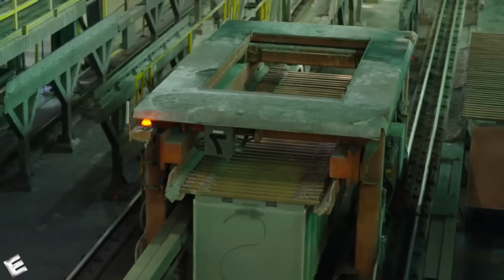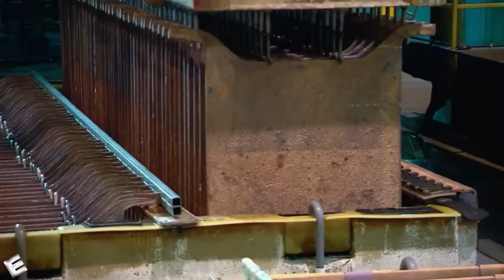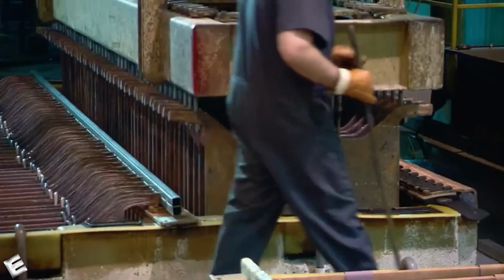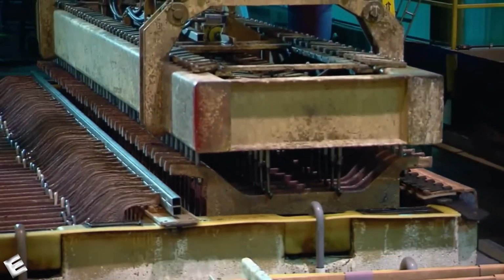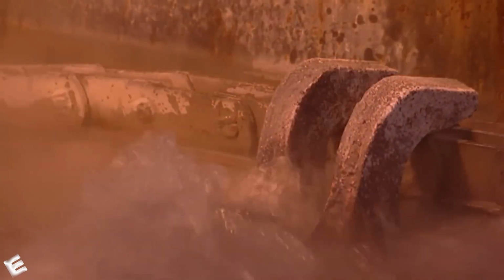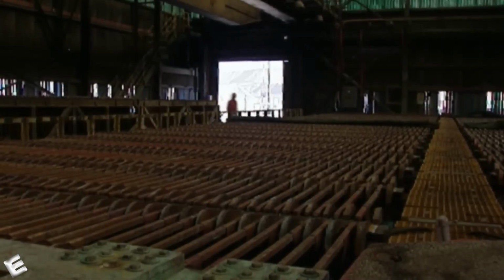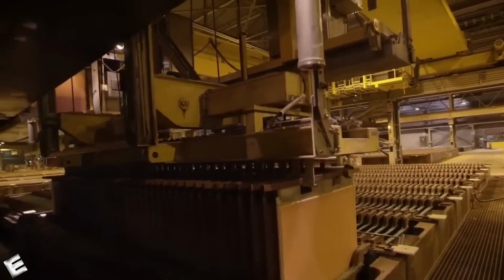The anodes are submerged in tanks filled with electrolyte and placed opposite thin metal sheets called cathodes. When an electric current is applied, the pure copper transfers from the anodes to the cathodes. The impurities fall to the bottom of the tank. The result is copper with a purity of 99.99%, suitable for manufacturing even the most demanding electrical cables.